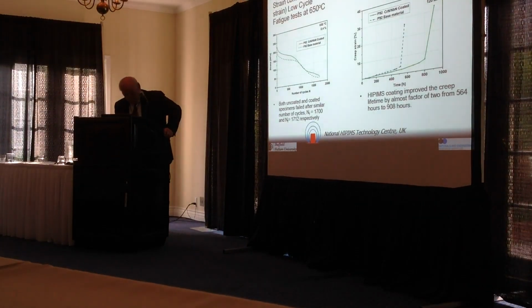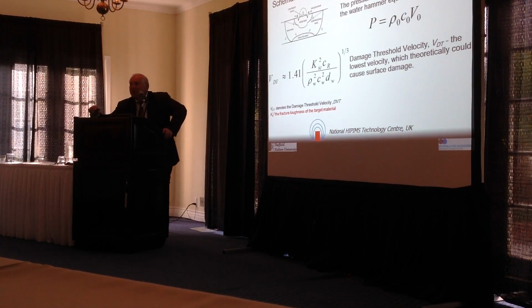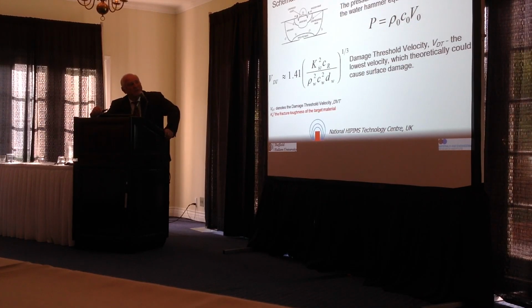We have preserved the fatigue resistance of the material. We have improved the creep behavior of the material. And very interesting results were coming from water droplet erosion tests. So that is the water hammer equation which shows the relation between the water pressure in the droplet and the critical velocity which starts producing first damage on the surface.